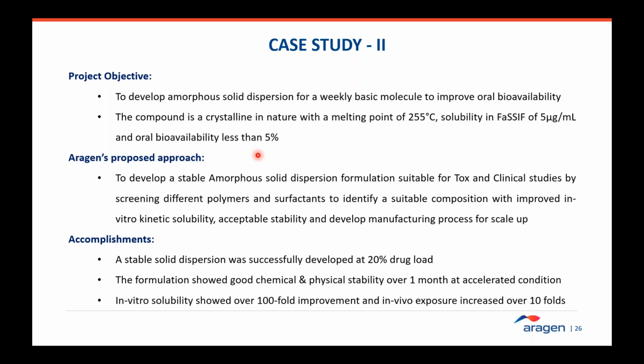The main issue with these kinds of compounds is they dissolve in low pH and then crash out, precipitate out rapidly at higher pH, after pH 4 and above. So that causes very little absorption. And then especially in preclinical species where the pH is typically higher, in those cases, these drugs won't even dissolve in the first phase, and that affects the overall viability of this compound.